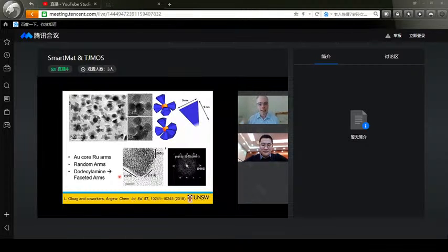The other important point is your choice of surfactant. If you're after specific facets, you need one that's going to bind strongly to your metal. So that's important. We use dodecylamine for the ruthenium. For the nickel, we sometimes use TOP as a surfactant as well, because that'll bind strongly to your nickel. So you do need to think of a few factors.